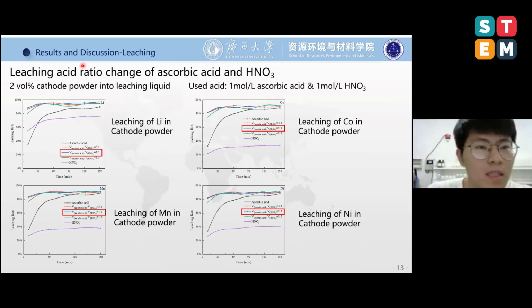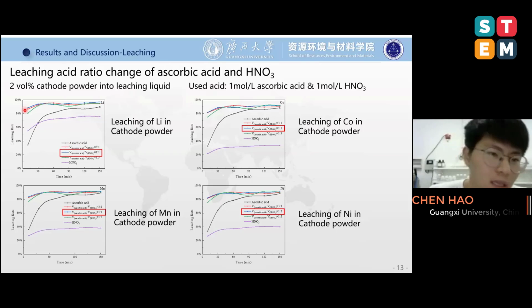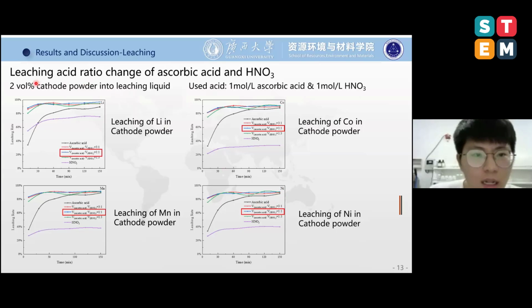At the third part, the leaching. First, we investigate the acid ratio of ascorbic acid and nitric acid. We put 2 volume% cathode powder into this liquid. The acid concentration is 1 mole per liter ascorbic acid and 1 mole per liter nitric acid. These are results. We can see for the lithium, when the volume ratio is 1:1, we can see the highest rate, similar to the cobalt, manganese, and the nickel. So for the acid ratio, we choose the 1:1.